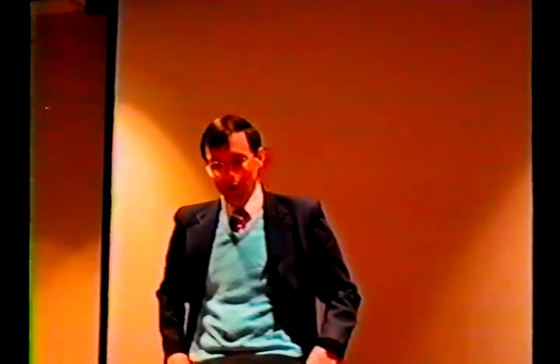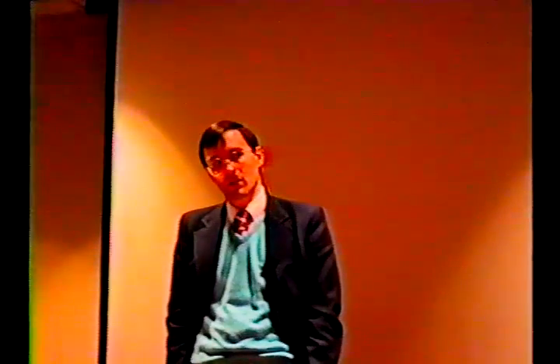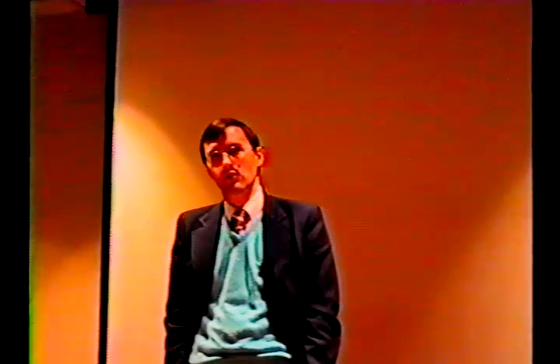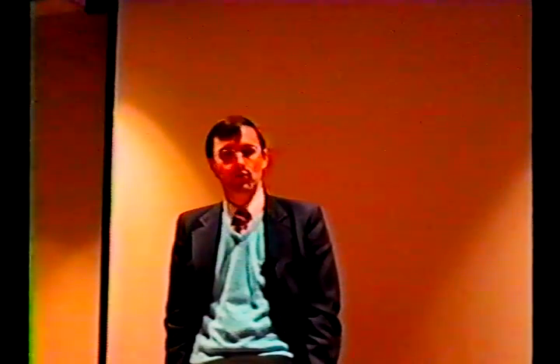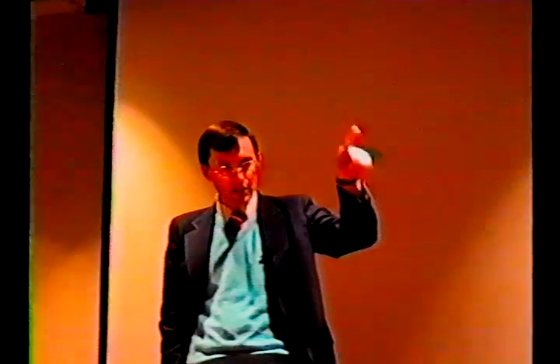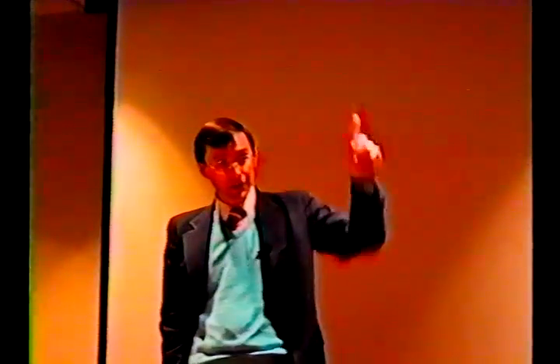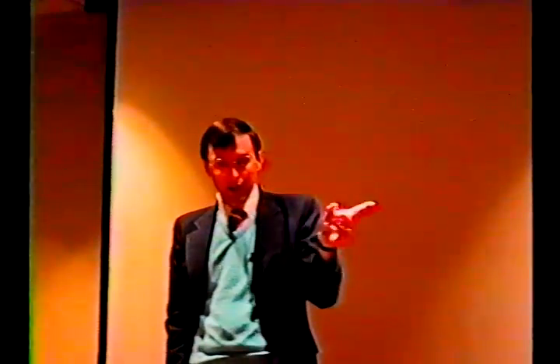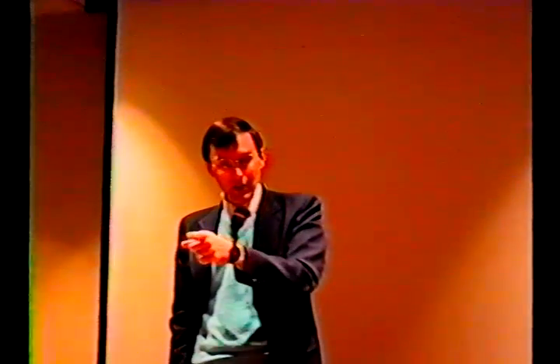And you'd like to compare all those, compare the infrared and all, and that's one of the projects we're working on right now. But I think you need a sensitive technique, and the nice thing about the fluorescence is you don't just have to take a steady state spectrum. What you can also do is do a lifetime experiment. Put in a pulse of light from a laser and look at the decay. And the rate of decay, rate is equal to A e to the minus kt. For a single exponential, we're going to get a straight line.